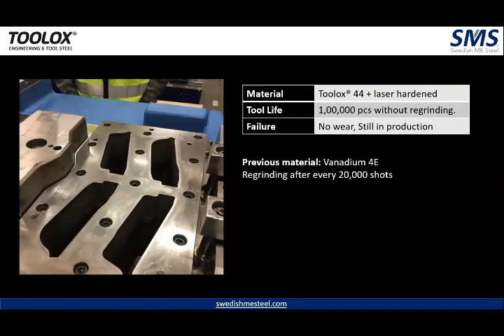What they faced was, even with the expensive metal, for every 20,000 shots, they needed to regrind it. But with Toolox 44 plus laser hardening, you could achieve 60 to 62 HRC with a case depth of 1 to 2 mm. We have done almost 1 lakh shots without any regrinding. And now that's a big benefit for you.